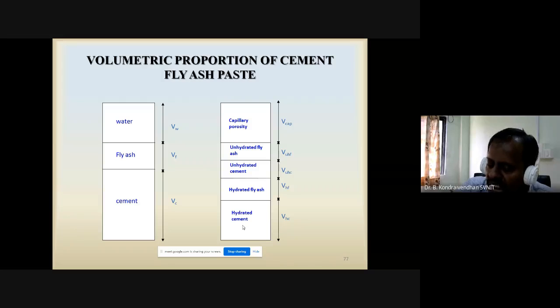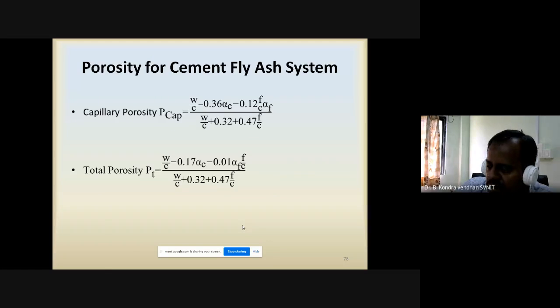First we calculated the hydrated cement product. We also calculated the hydrated fly ash product, and the unhydrated cement and the unhydrated fly ash. Then initial volume minus this, we calculated the capillary porosity. And the capillary porosity divided by the original volume, or initial volume, will give you the capillary porosity. Okay, so total initial volume we know. So what is the capillary porosity? We can easily calculate, because porosity is volume of voids to the total volume. That's how we calculate the capillary porosity.